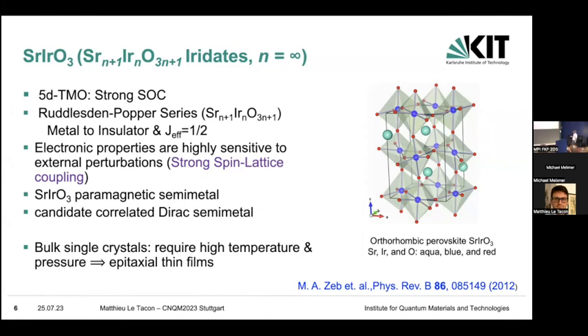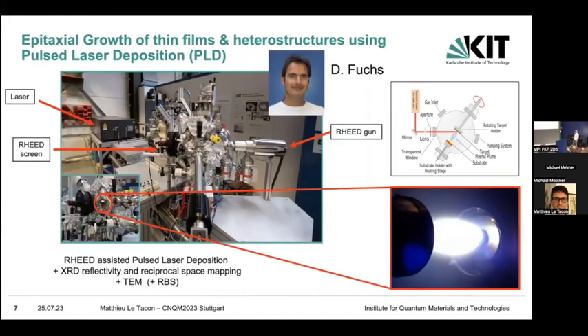Now, growing bulk single crystals of this material happens to be quite hard. It requires high temperature and high pressure, so it's much easier to actually grow thin films and stabilize them that way. But there again, there are a lot of complications related to the actual structure that you manage to stabilize in a thin film. So it took a lot of work for Dirk Fuchs to find the good conditions to grow the right phase, and to control that phase and its structure. I'm going to show some examples.